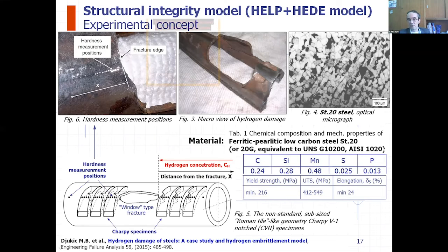We investigate typical ferritic-pearlitic, low carbon St20 steel, equivalent to 1020 steel. And we use the non-standard subsized specimen, as you see, of Charpy V-notch geometry. So it's a subsized specimen in order to provide a specimen from the tube wall.